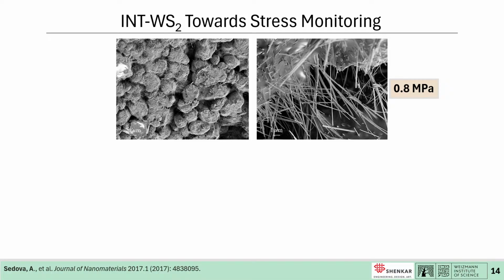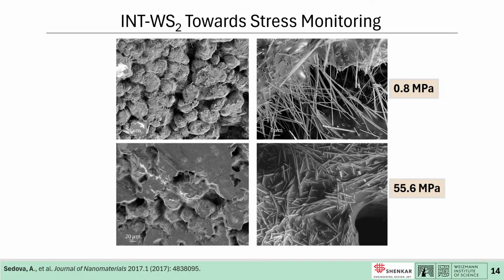When we applied a relatively low pressure, we could see that the nanotubes were basically touching each other. So it's what we were expecting to achieve, that the nanotubes would touch each other and the electron would be able to hop from one nanotube to the other. But when we increased the load, basically the same thing happened as with dispersion. The polymer went in between the nanotubes, and we could not achieve the results that we were expecting. So we were working with samples that were prepared with a low load.